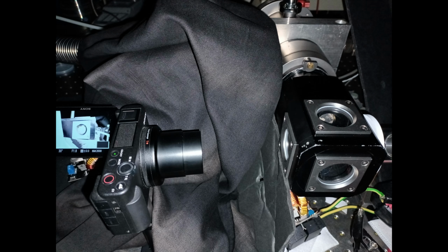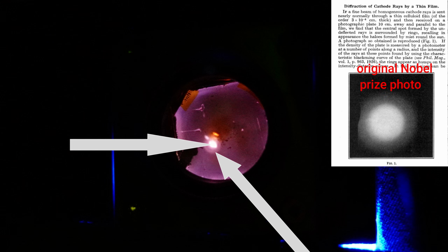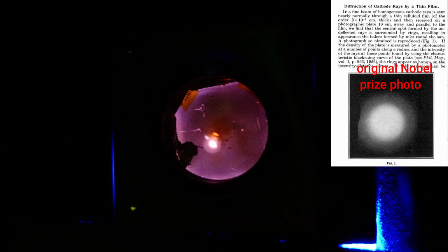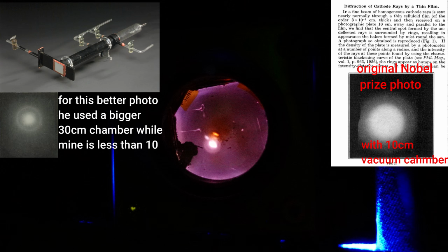But after some time I got this image, where we can clearly see the transmitted beam and the halo around it, of the same order of magnitude as the image collected by Thomson in 1927. The main difference is that he had a much longer distance due to his vacuum chamber being bigger, so he could see a bigger image over longer distances. The circular halo is not present in the absence of cellulose.